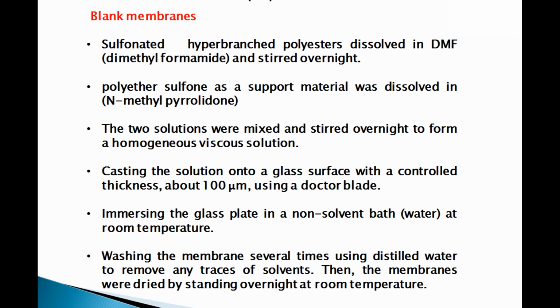Then the solution is cast onto a glass surface with a controlled thickness of about 100 micrometers using the Dr. Blade plate technique. The glass plate is immersed in a non-solvent bath of water at room temperature, and the membrane is washed several times using distilled water to remove any traces of solvent. Then the membrane is dried by standing overnight at room temperature.